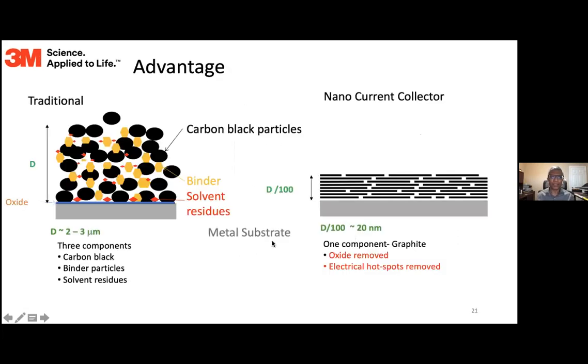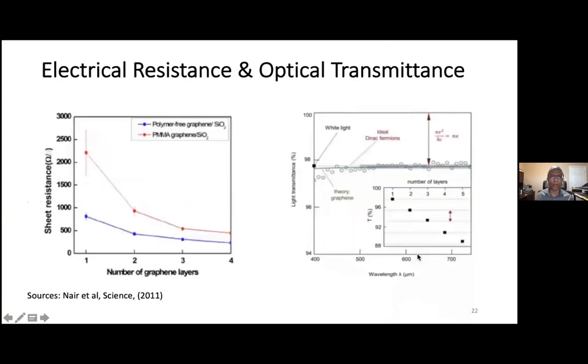So this is the final slide on that section. Typically, before this came along, people were using a very thick coating, like a micron thick carbon black coating at the interface, whereas we can replace it with a very clean interface now, both chemically and electrically, which makes the battery work better. But now we understand why it's better as well. So let me turn now to graphene, real graphene.